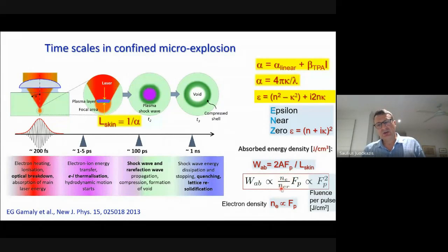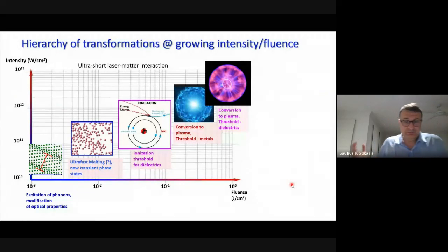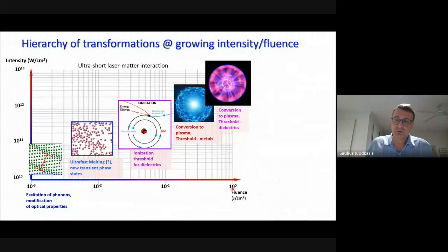When their concentration is reaching critical concentration given by wavelengths of light, this would be the condition when energy absorption is saturated. So when we are playing with intensity in those conditions, epsilon near zero, in order to have the strongest energy deposition. So with the 3 orders of magnitude, which is very easy in terms of fluence, and this will be the same 3 orders of magnitude in terms of intensity, with a very simple tabletop, not expensive laser these days, we can actually make any transition we want in material.